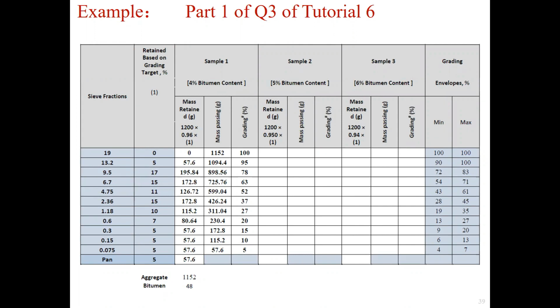The mass passing is the mass of the aggregate minus the retained mass from each sieve. And finally, the grading is calculated using the passing mass divided by the mass of the aggregate, 1,152 grams. We could do the same way and complete the table for different bitumen content.